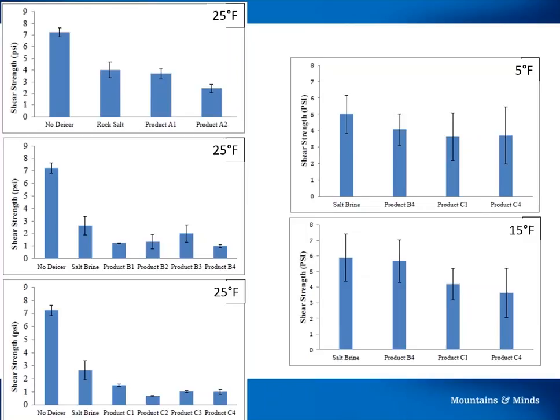So each pavement sample for each product type had 6 replicates run, and this data is a combination of the 6 replicates. So it was repeated for multiple pavement samples for multiple replicates. And you can see here that the error bars are pretty significant. But as a general trend, you can see that for some of these products, they actually function really well at low temperatures as anti-icers.